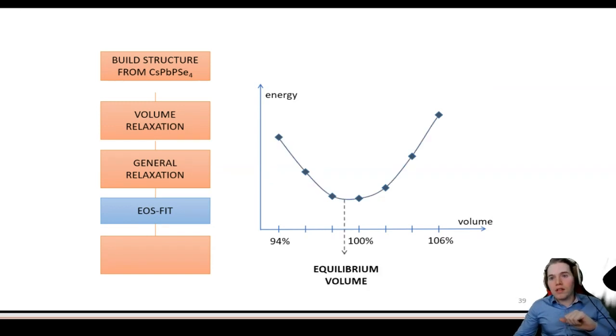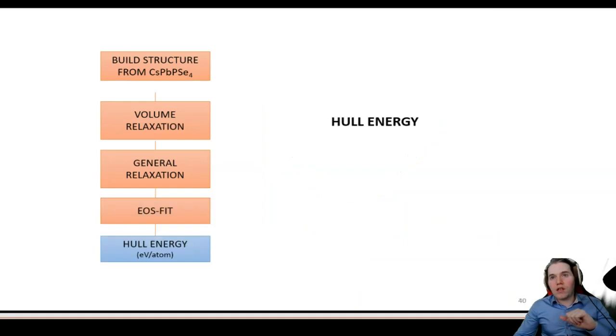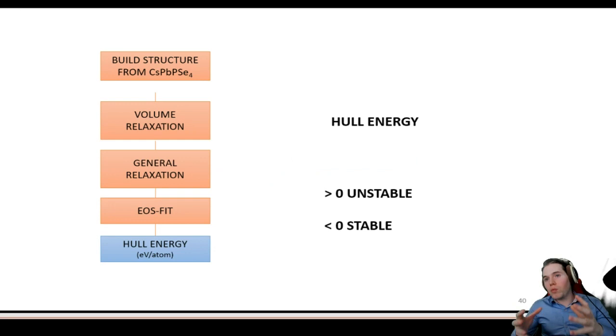All right, so we use this to get a final volume, and then we calculate this formation energy. If it is smaller than 0, meaning you gain energy when you create this material, then we say it is stable. If it's positive, meaning it costs energy to make this material, then we say it is unstable. Okay, we normally take a safety margin, but that's not that important right now.